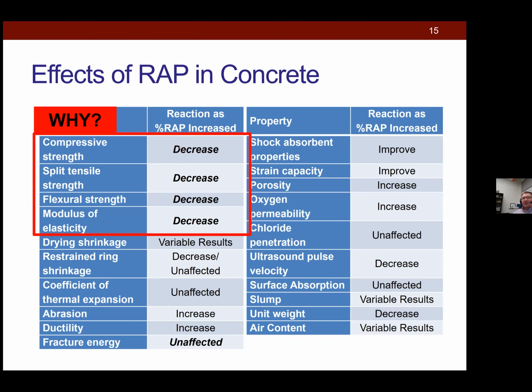So the question is, why do we have this decrease? And if we can figure out why we have this decrease, can we then figure out how we can mitigate that decrease, and actually improve the properties, okay? So this isn't as simple of a problem as just adding silica fume, okay? So you can look at a lot of your SCMs. If you add some slag, add some silica fume, you typically will densify the ITZ, reduce some porosity, produce more CSH. That all sounds great, but we didn't see that effect with RAP and concrete.